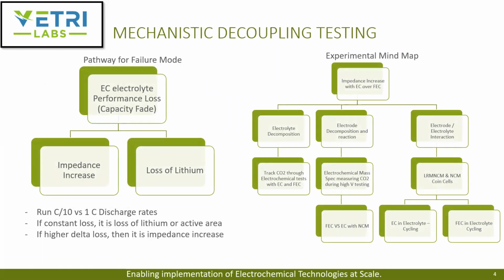In terms of decoupling tests, the first step they address is the pathway to the failure mode. The capacity fade is the main problem statement, and they look at both impedance increase and loss of lithium as the reasons for capacity fade.